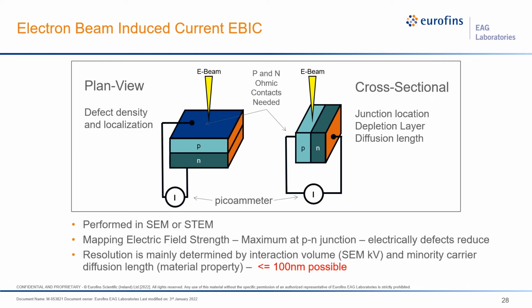And typically the maximum is at the PN junction, and electrically active defects in the sample are going to reduce that and appear as dark spots or dark regions where you're having localized recombination. And then ultimately you can do it in plan view, where the beam is normal to the junction, or you can also do this in cross section where you're rastering the beam across the junction.